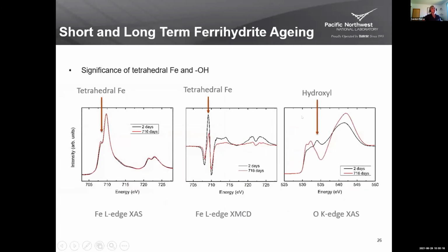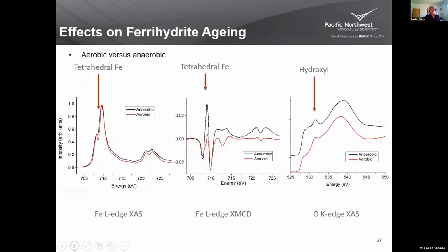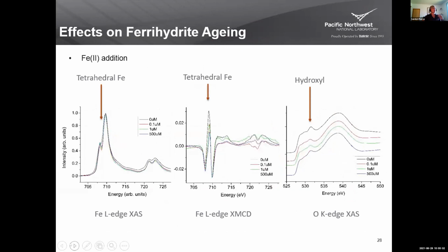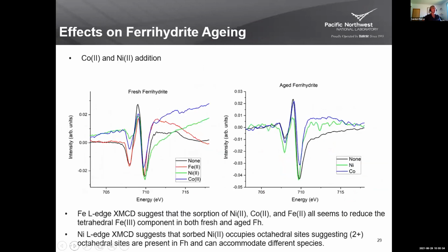It's also correlated with the concentration of hydroxyl groups in the structure that are actually acting to stabilize that disordered tetrahedral site. And a number of things will influence it, including whether you age under aerobic or anaerobic conditions, whether you add in iron 2 during the aging process, or whether you dope with cobalt or nickel as a non-redox active proxy for iron 2, to understand where they might be affecting the structural transformations.